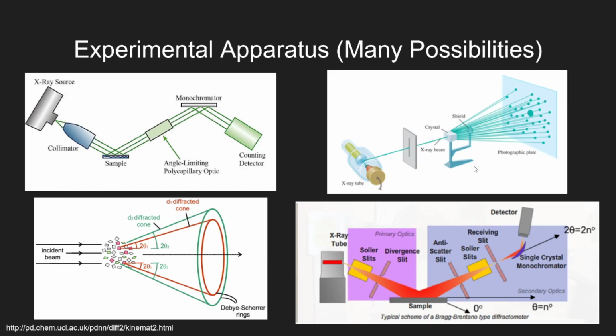And then some other experimental issues that we might run into are absorption effects. X-rays are not perfectly reflected all the time. They can be absorbed by the crystal, and that can cause issues in terms of intensity, meaning that some of the X-rays don't all come out, and if there's a lot of background noise, then you might not be able to get as high of a peak as you want, and it might cause you to have poor data.